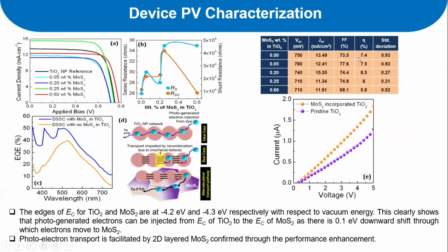That shows the photo conversion efficiency 7.4. So that is very clear that we have considered a working device, and then we started to introduce 2D layer semiconductor into the titanium dioxide electron acceptor after removing the organic dye molecule. In that particular case, we started with 0.05 MoS2 (molybdenum sulfide). That increased the voltage, and we got a little less current, and it resulted in efficiency 7.5. So that closely matches the reference device.